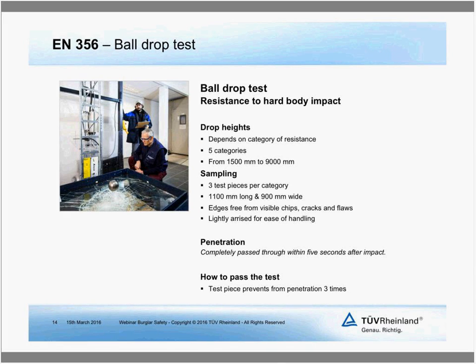So the test is quite severe. And what you will see is that if you have a very rigid sample, the sample will most of it break, but the ball will be reflected by the impact, and some get as high as 2 meters in the air again. It is performed at room temperature. The temperature is described in the standard. The humidity here is not described, but at normal room temperature the test can be performed. And after each impact, the loose fragments shall be removed so that you have a reproducible test. And if you perform the test again, you should get the same test results, or at least as close as possible.